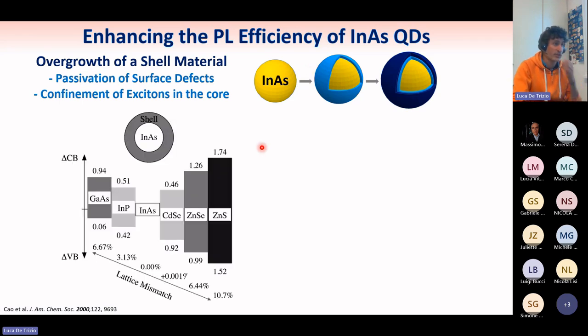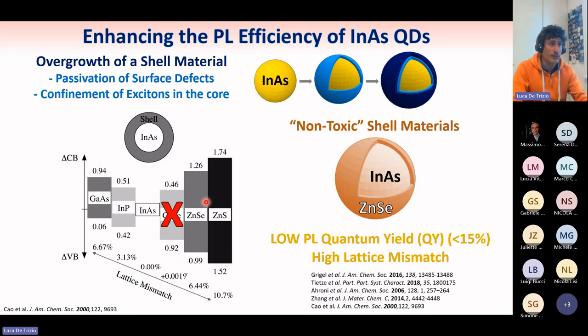If I now check the shell materials that I can use to cover indium arsenide, these are the most common ones. And if I exclude cadmium for toxic reasons, you can see that the choice is quite limited, and the lattice mismatch, expressed here as a percentage, is typically quite high, especially from indium arsenide to zinc selenide. And indeed, people reporting this kind of heterostructure so far got quite low quantum yield, that is the efficiency of the system. Why? Because there is a quite high lattice mismatch.